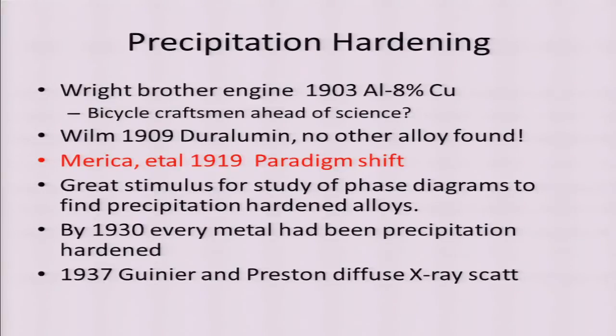And within 10 years, every metal had been hardened in one way or another by precipitation. And it's a wonderful way of hardening material. And it also led to beautiful work on phase diagrams that now became important for development. And of course, in 1937, Guinier and Preston, with diffuse X-ray scattering, discovered that, and this is the beginning now of diffuse scattering as a way of testing things that are too small to be seen in a microscope.